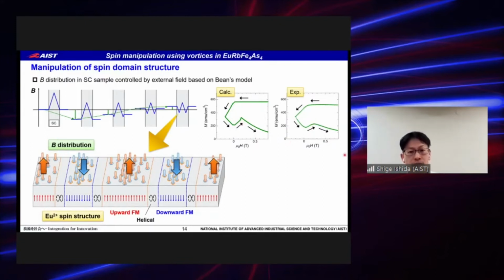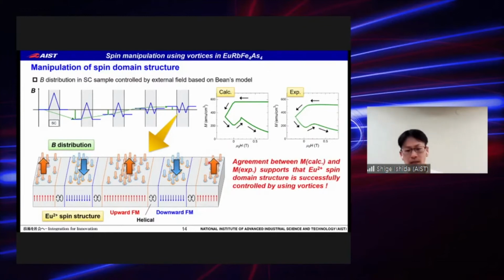So the agreement between the calculation and experiment supports that the helical spin domain structure is successfully controlled by using vortices. Such spin manipulation may open a way to novel device applications such as superconducting memory. Thus, europium rubidium 1144 is a very interesting material in terms of basic research and applications.